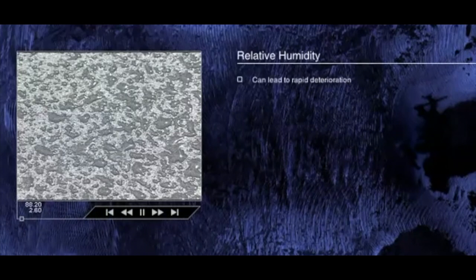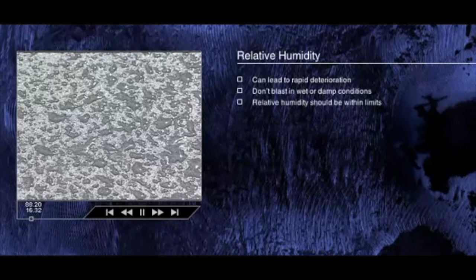When blast cleaning, high humidity, moisture, can result in rapid deterioration of the cleaned surface. Final dry abrasive blasting should not be performed in wet or damp conditions, that is, when raining or when the relative humidity is very high, generally greater than 90%. Relative humidity is defined as the amount of moisture, water vapor, in air compared with the maximum possible in the air, i.e. saturation level. If RH reaches 100%, then the air will not support any more water vapor, and a surplus would appear as condensation.